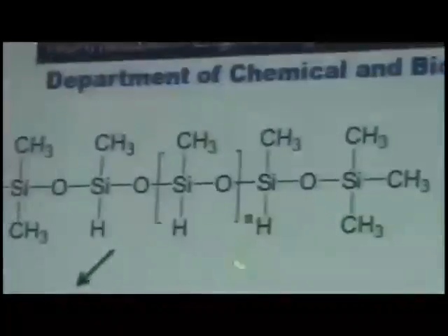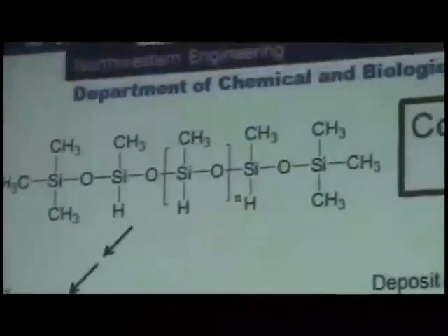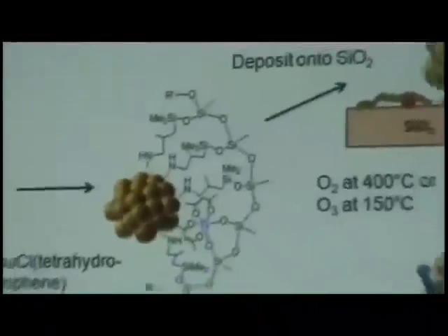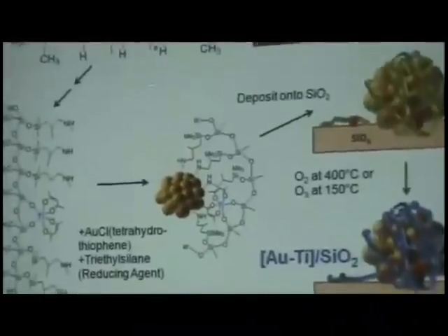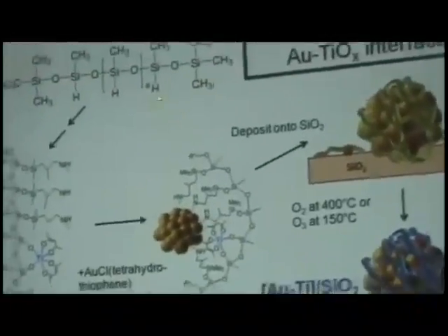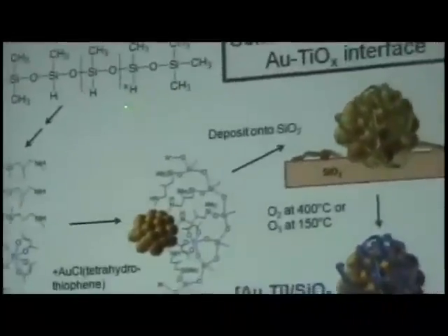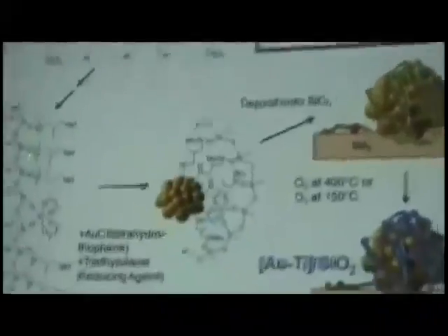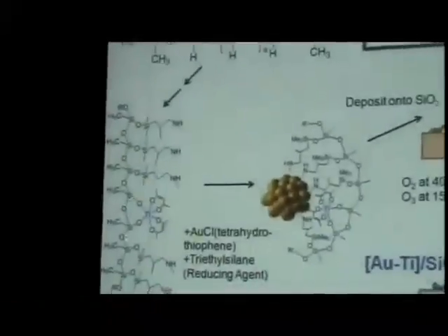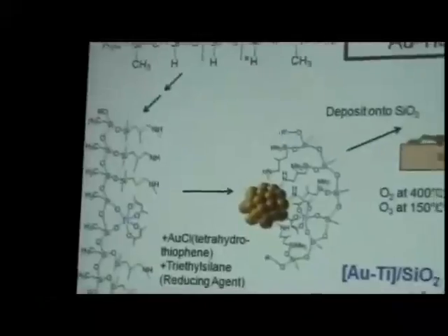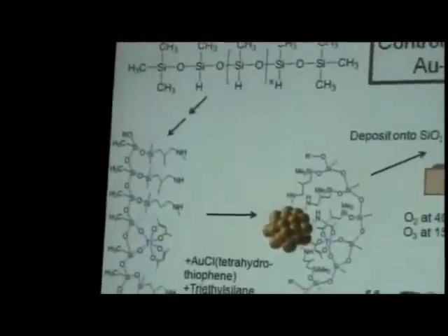Well, first of all, we can follow this reaction quantitatively with NMR. This reaction with amine is quantitative. This reaction of oxidizing the silane to silanol is also quantitative. So knowing the size of this molecule, we know exactly how many silanols we have. Then the quantitative reaction lets us know exactly how many amines we put onto it per molecule. Likewise, we can also know quantitatively how many titanium per molecule.